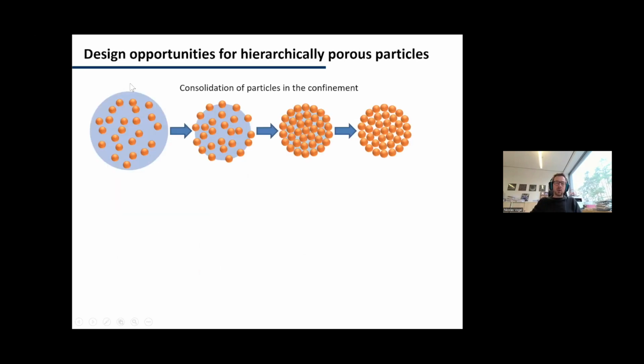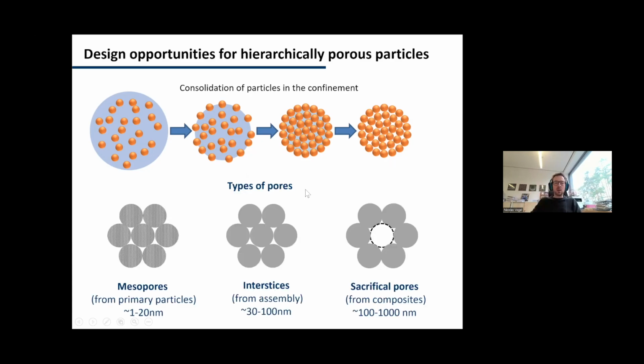If you again look at the fabrication process, you see we have the particles here in an aqueous dispersion, and as it dries out, it eventually consolidates. And here you can already see that by changing the primary particle size, we can create different porosity simply because that is inherited by the interstitial sites of this colloidal packing. But we can also leverage different types of pores. We can make smaller pores simply by using porous primary particles, zeolites, mesoporous silica, metal organic frameworks, and these types of things. And we can introduce larger pores by introducing polymeric particles that we can then either dissolve or burn away. Or we combine all of these to make a hierarchical material.